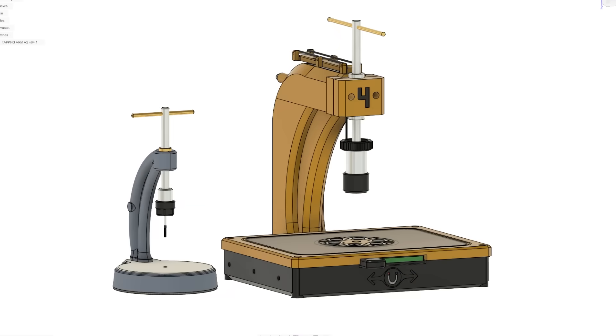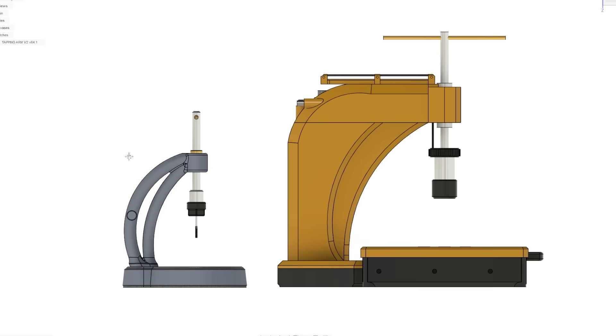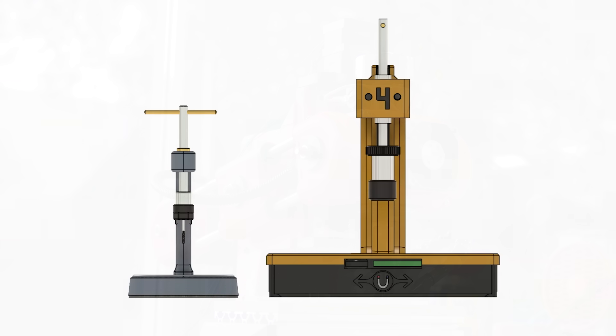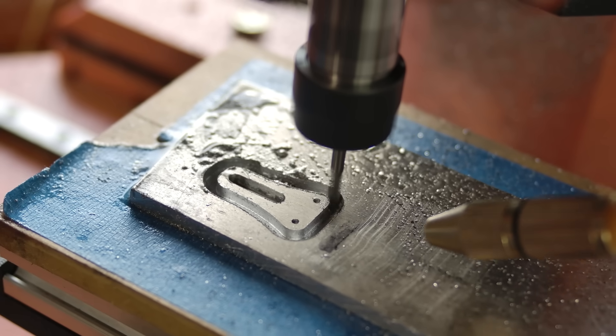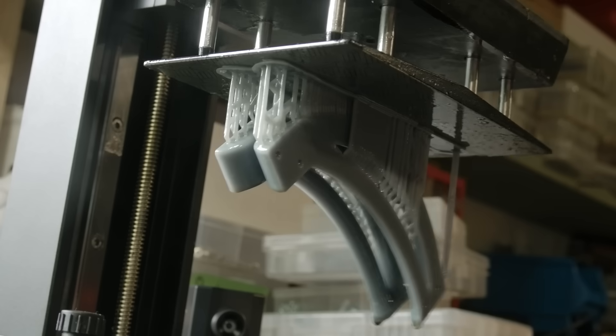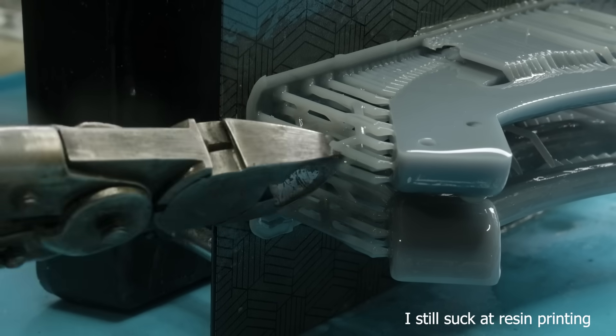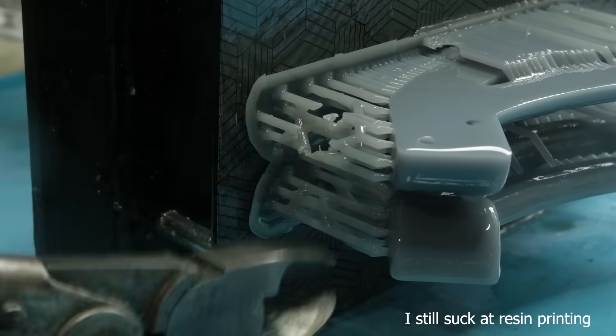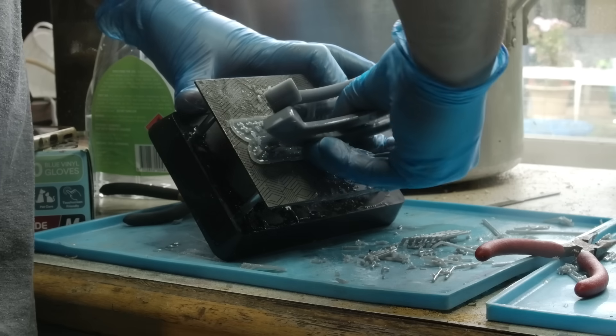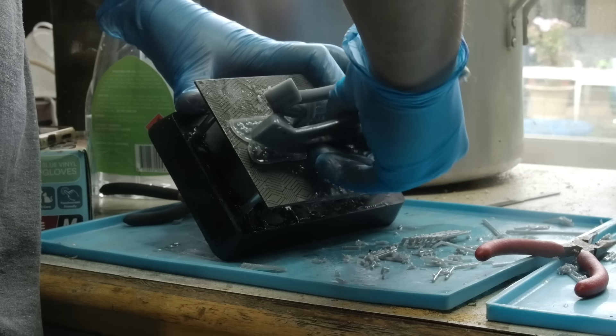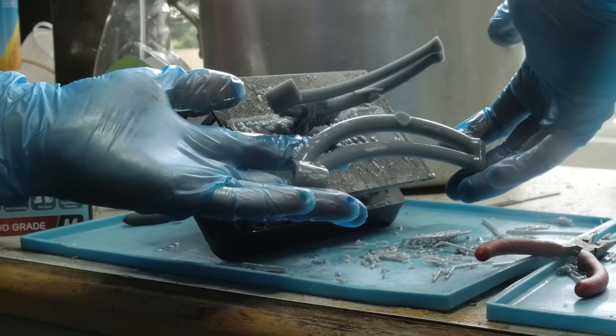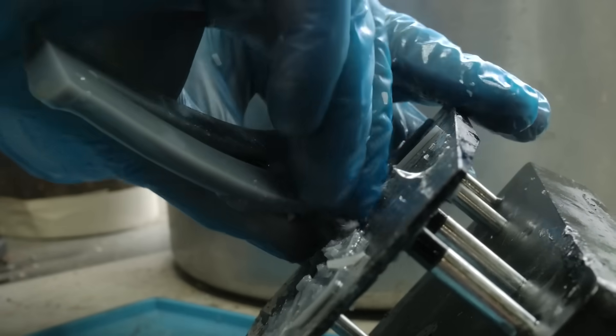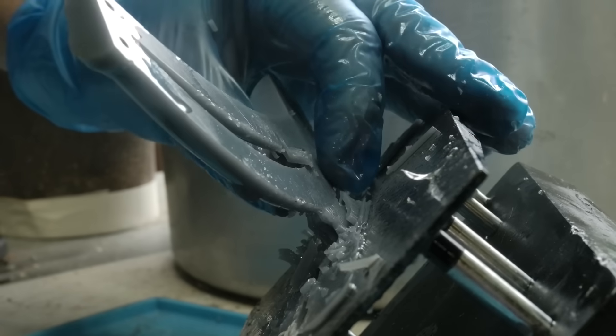I love the design language of casting and how it differs from my 3D printed offerings. The printed tools have huge, bulky shapes, a necessity to overcome the weaknesses of the material being used. Working in metal, but especially cast metal, goes to the complete other end of the spectrum. Not only can the parts be more elegant, they have to be. Excessively thick and bulky parts are prone to voids and shrinkage, so designing things that can cool down evenly is essential.